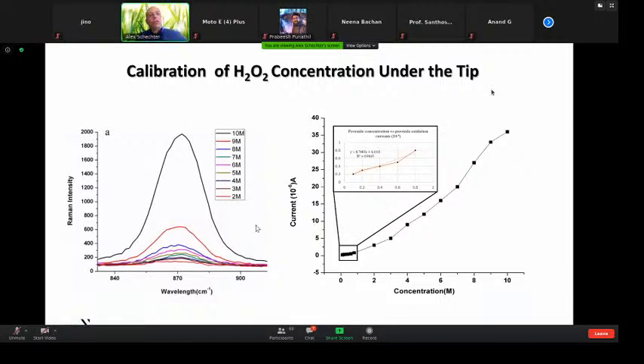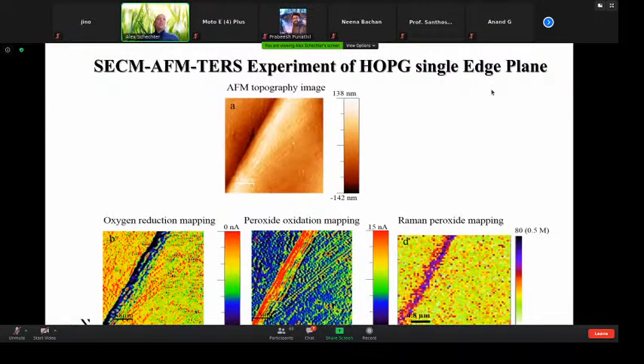So the next step was to measure all 4 things simultaneously. We can measure the topography of the HOPG, of the electrode. We can measure now the oxygen reduction at different locations with a spatial resolution of around 20 nanometers. We can measure the peroxide formation here of the same unit area, and now we can also measure the peroxide itself, the intensity of the peak that comes.